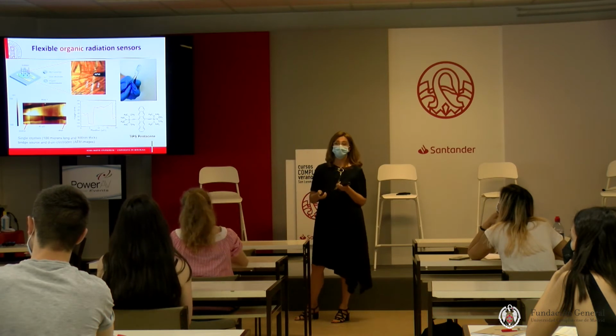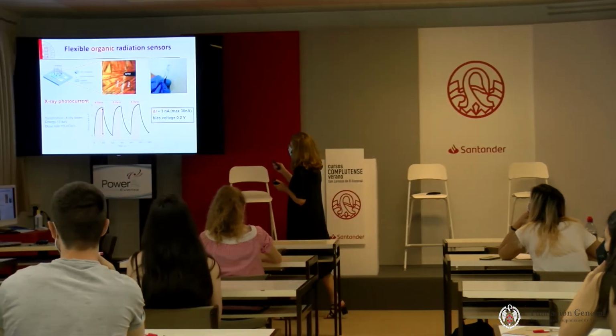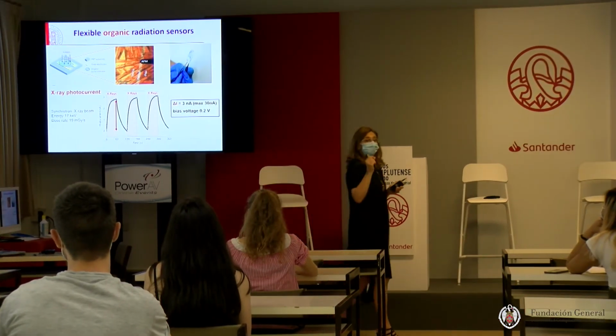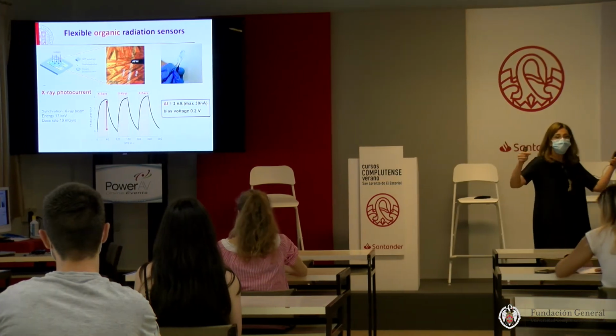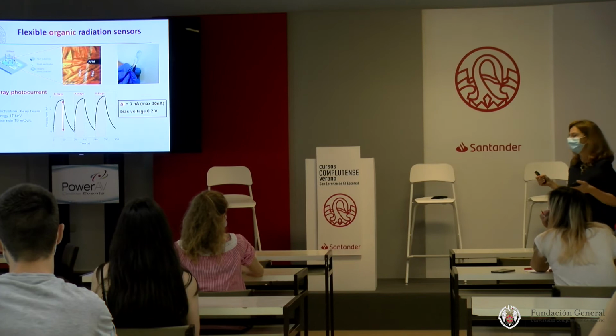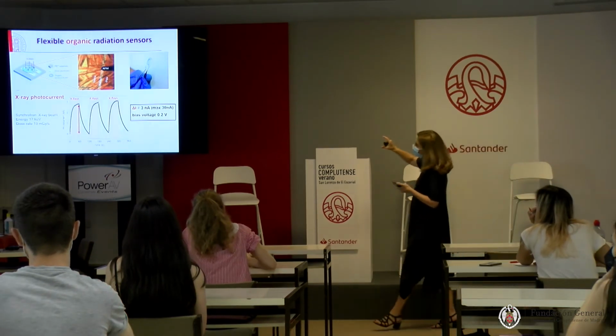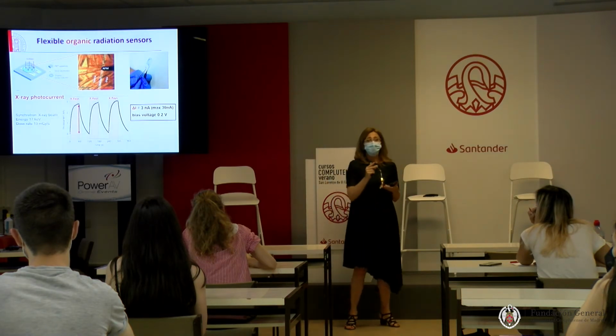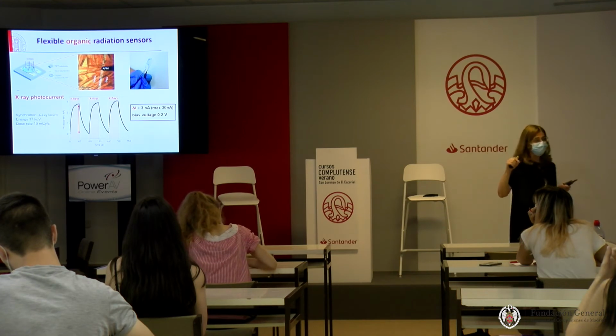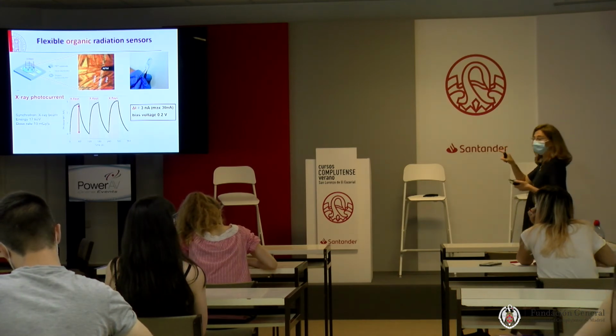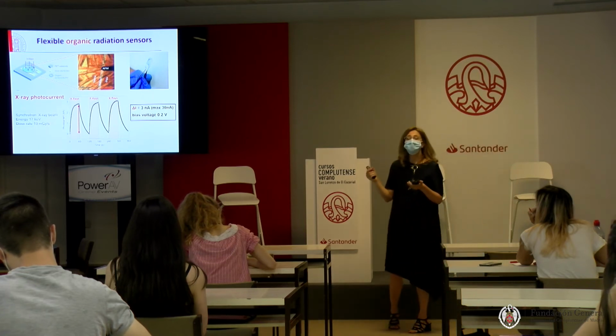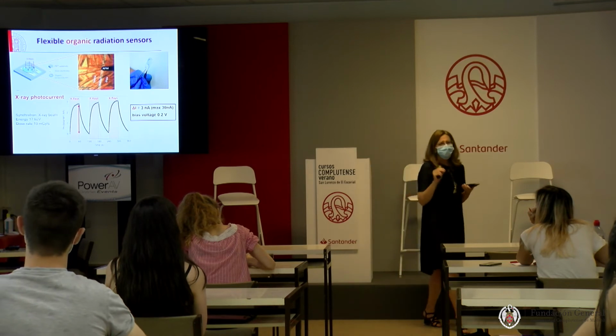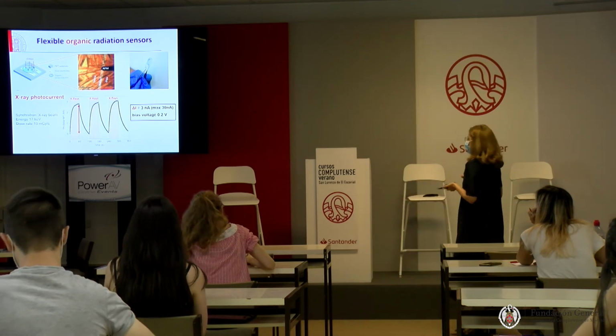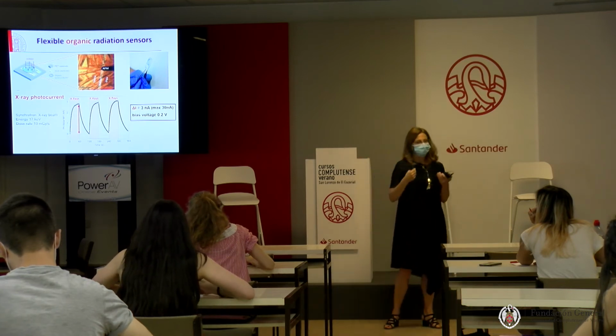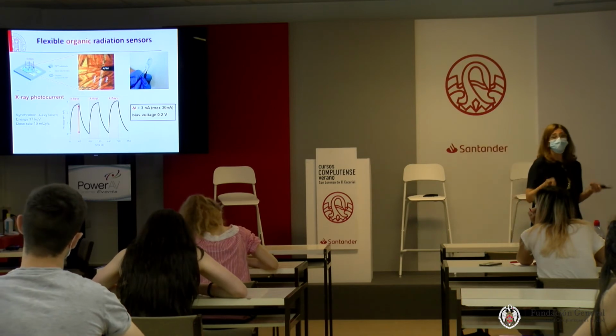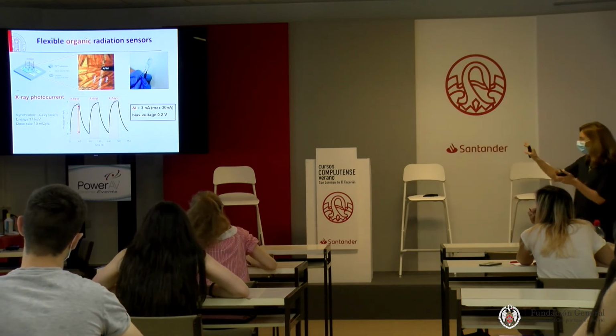These devices are definitely flexible because they're so thin. And what is interesting, they respond very nicely to X-rays. So, X-rays on-off, you see an increase in the current measured between the source and drain. Very clear increase. We call the delta I the increasing photocurrent. Two important points. This delta I is reproducible, stable, and we can extract the signal at 0.2 volts. That means if we want to operate this device, we really need very, very low power. Typically, a very good inorganic detector that operates and gives you much more information than this one may require up to 100 volts to be operated, but it tells you more. But it's not really easily there.